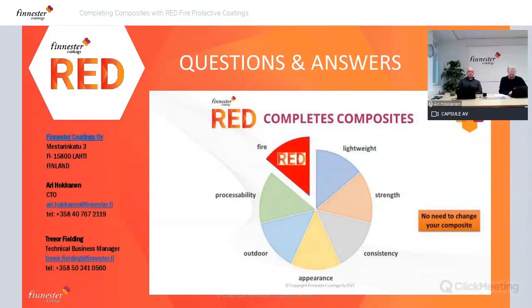Gas permeability is. Oh yes, there were some questions on the weights. So typically, what areal weight is applied on a composite panel? So what film thickness? 400 plus 400 grams per square meter is the standard to begin. You get very nice protection with 400 plus 400, 800 grams per square meter, which is approximately 600 microns total film thickness. But sometimes just a single coat application will do the job as well.